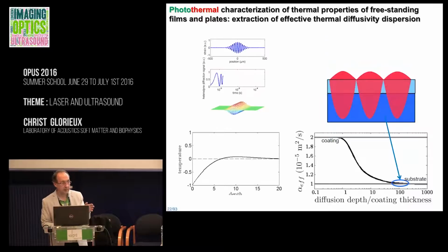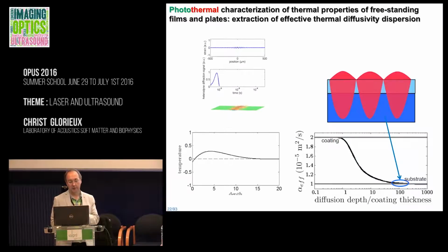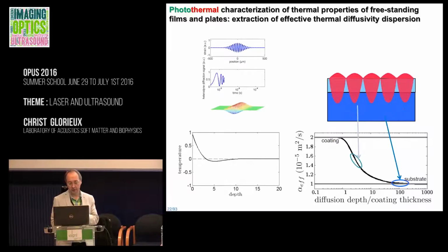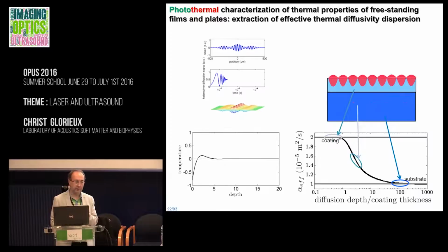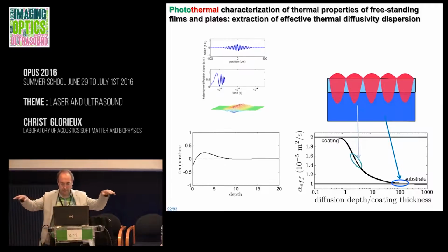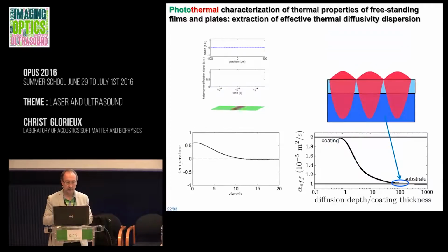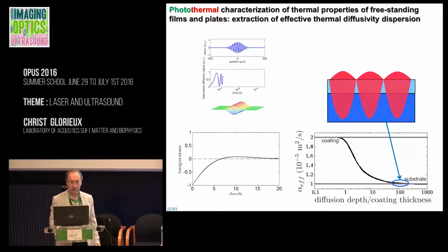Interestingly, this talk is about light and sound, but I still wanted to say that you can also exploit the photothermal effect, because as we have seen, we have also this thermal expansion, which is disappearing depending on time, and this decay time is related to the size of the grating, because a big grating takes more time for the heat to diffuse and to remove the grating, while a very narrow, fine grating is much faster to remove by thermal diffusion, and we can exploit this.